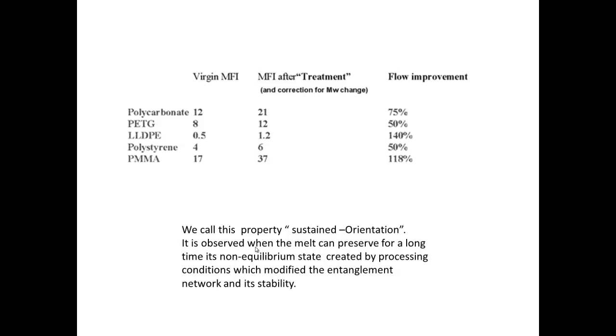Here are some values obtained for what we call, therefore, this property, sustained orientation. You can see that for polycarbonate, for instance, we have a virgin MFI of 12, which goes to 21. PETG, 8 to 12, 50% fluidity improvement. LLDPE, 140%. Polystyrene, 50%. This was the old value. It's actually more now, recent,